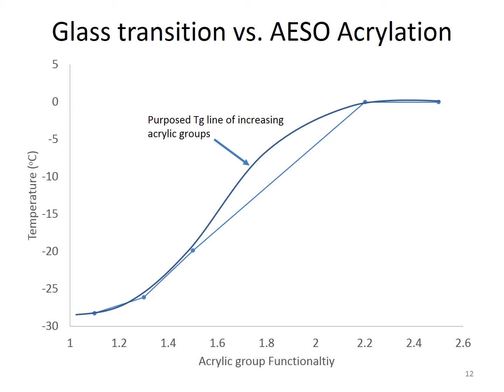All right, and then we can do those polymers, and then we can look at the effects in modifying asphalt, and we can take a PG 51 grade and make it a 64, or we can even push it up towards a 76 with 3% modification. But if we drop down in this acrylated group functionality, we actually can now move towards using a cyclohexane, which is more of an off-the-shelf solvent for producing polymers, and then the solvent removal process is easier. But we also find that we get better conversion quicker in producing our polymers. So we can move from 10 or 12 hours in producing the polymer now down to the 6-hour range.